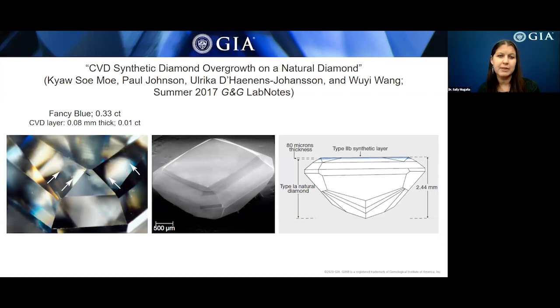Continuing to discuss that same diamond, several other measurements also confirmed the composite origin of this stone. A distinct boundary line indicating that interface, which is marked by arrows on that leftmost image, was seen under the microscope. In the middle, we show an electron microscope image combining secondary electron and cathodoluminescence images that also confirmed the presence of that overgrowth layer and that interface between natural diamond and CVD diamond. And then at right, we have a schematic showing the CVD laboratory grown layer is approximately 80 microns thick, about the width of a human hair.